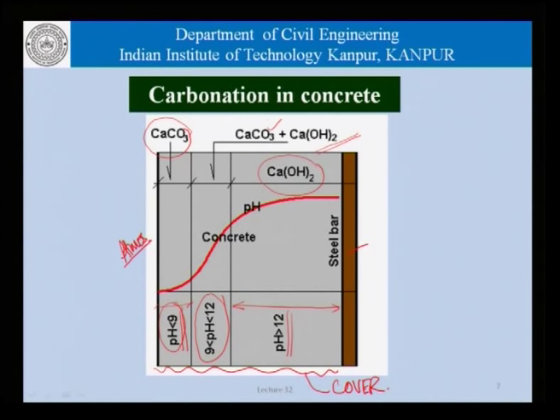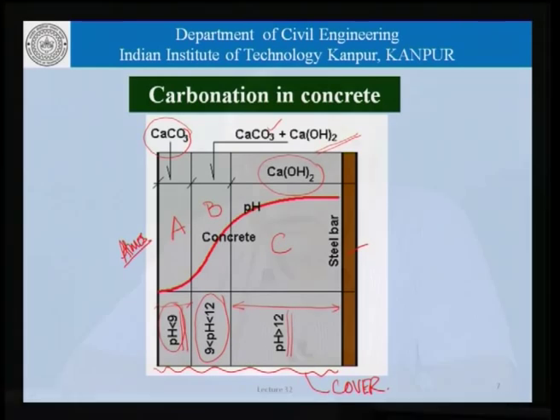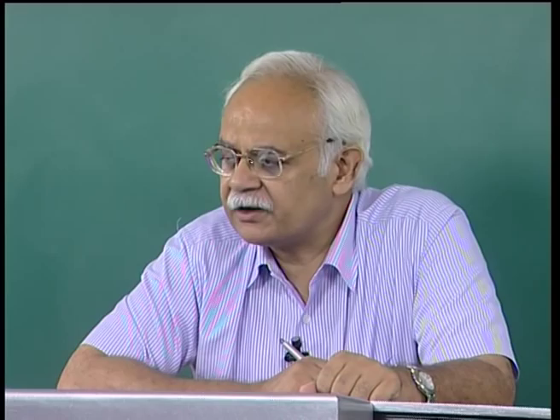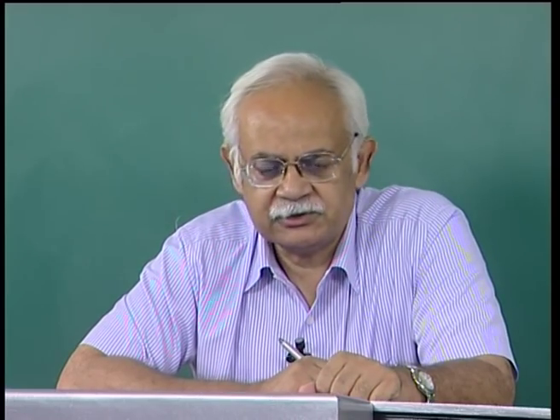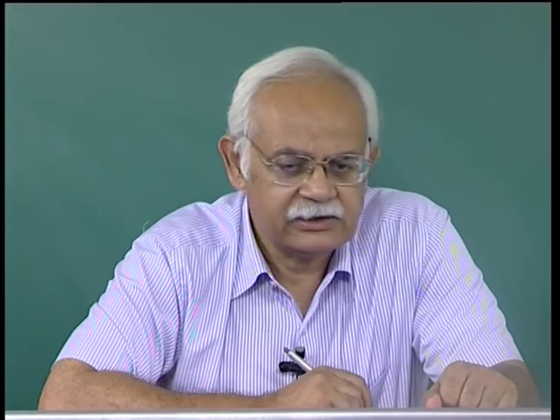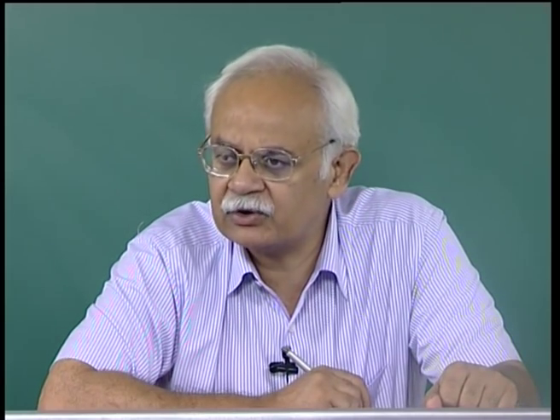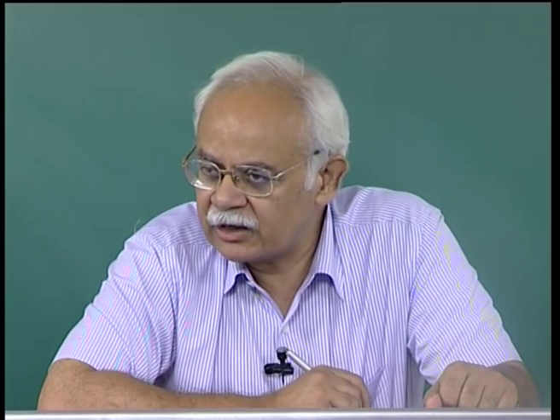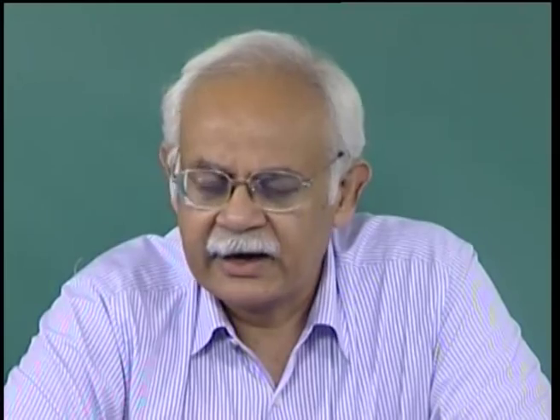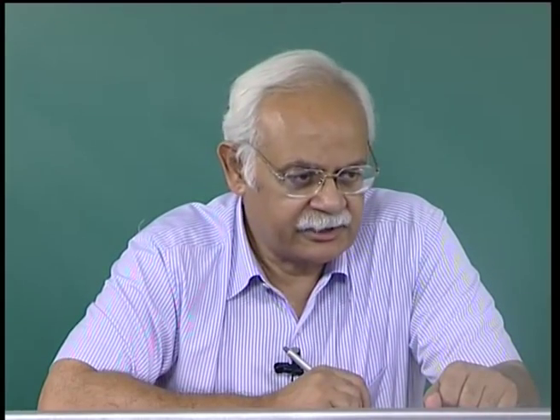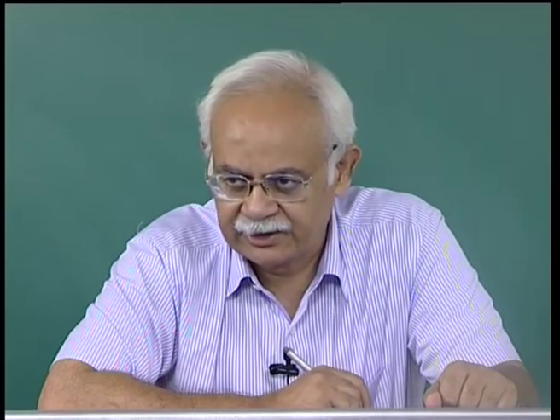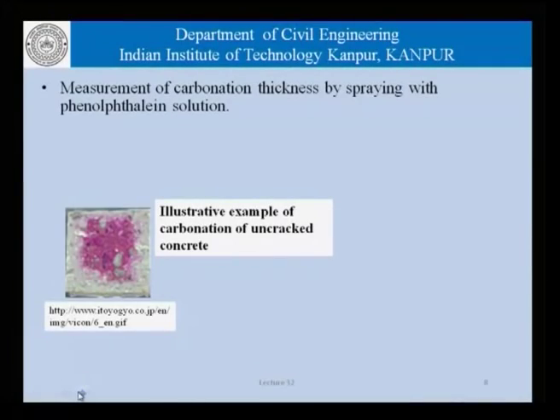So, we are trying to divide the cover concrete into a zone A, B and C, where zone A is a zone where most of the calcium hydroxide has been consumed and a lot of calcium carbonate has been deposited. Zone C is largely unaffected, and therefore, there is practically no calcium carbonate there, it is all calcium hydroxide, and zone B is still in the transition where some calcium carbonate is there and there is still some calcium hydroxide. So, with this model understanding, let us try to see how the carbonation is measured in concrete.